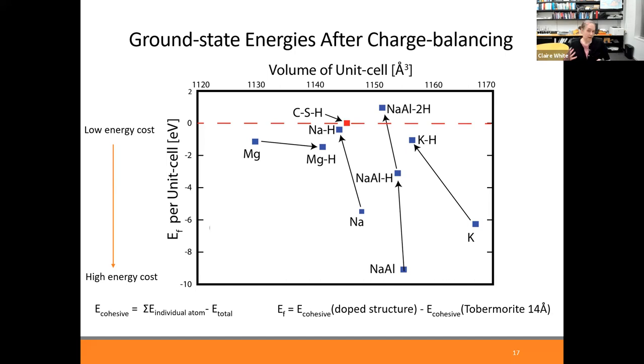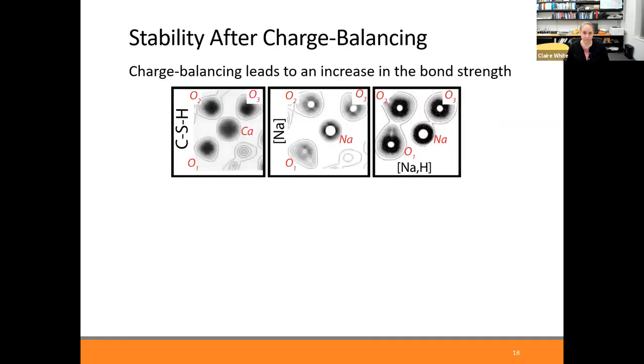Now you might say, okay, why a hydrogen? Why not another atom? And we also tried one calcium for two sodiums. That's not as energetically favorable. So we found that the hydrogen atom, probably because of its size, is favorable to have. Whereas if you're looking at, say, two sodium, they take up too much room, and that's causing some of the issues when it comes to the overall energy of the system.